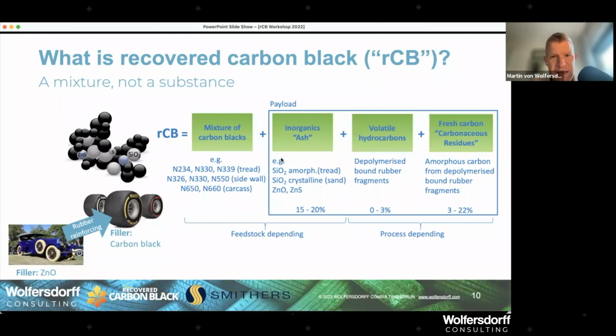But in Europe, the US, and increasingly in China, the tire industry is using precipitated or amorphous silica as a filler in the tread. And the undesired silica compound is the crystalline silica, which is also known under the name sand. Sand coming just from road debris and either from the use time or from where the tires have been stored. And sand, when we mill the recovered carbon black ultra fine, under 10 micron, the crystalline silica under 10 micron becomes a respirable crystalline silica, and that has a carcinogenic effect if you inhale it. Of course, you would never inhale that crystalline silica coming from the recovered carbon black, because the recovered carbon black would be used in the tire, bound in the rubber matrix.